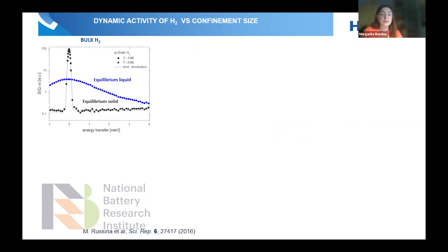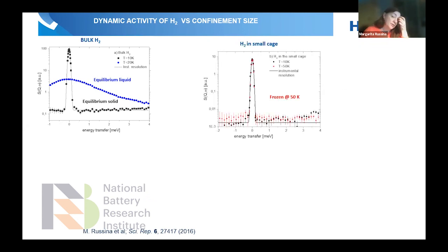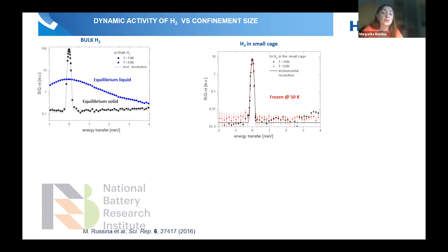And it turned out, you see here the bulk hydrogen itself. At 10 Kelvin, we do not see any signal. At 20 Kelvin it's already melted, and we see a broad Lorentzian. But when we place the hydrogen in the small cage, we see that it remains frozen at temperatures as high as 50 Kelvin. And when placing the hydrogen in the large cage, we see the completely opposite.